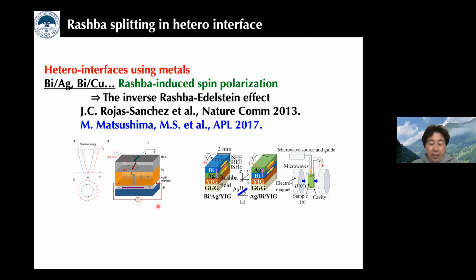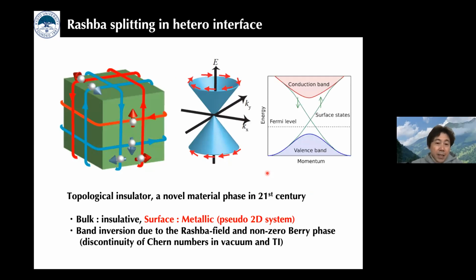of the electromotive force. And my group was also doing similar work by choosing Ag as a spin source. And also we can control the stacking direction of bismuth and silver, which allows a more precise estimation of the spin conversion efficiency. The second important system with Rashba splitting is, of course, the topological insulator.